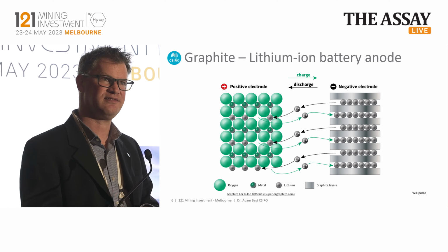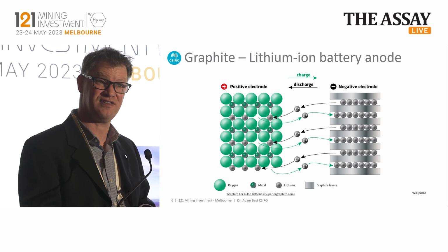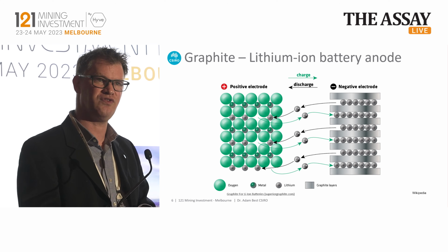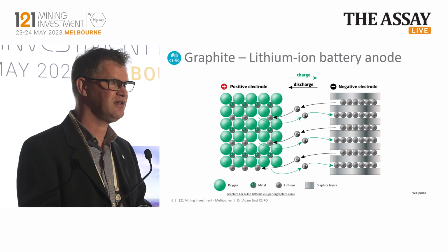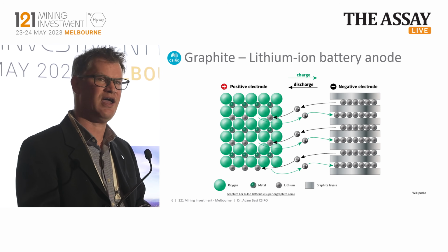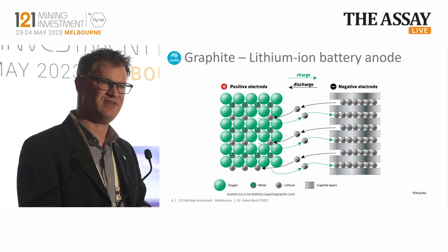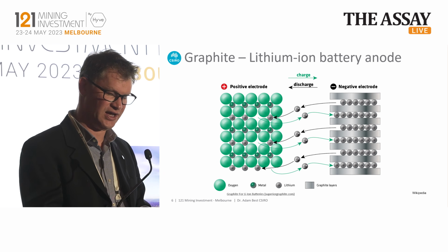Additionally, you're now starting to see companies adding small amounts of silicon to these anodes in order to further boost the energy density of batteries, and most commercial cells now have between 4 and 7% silicon additive to increase the specific energy of that negative electrode.